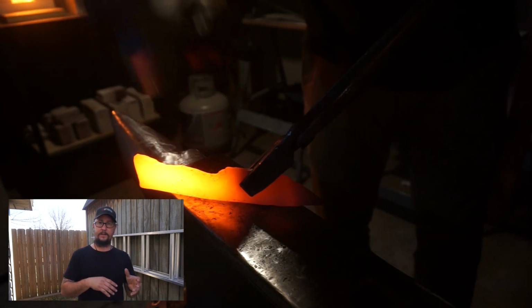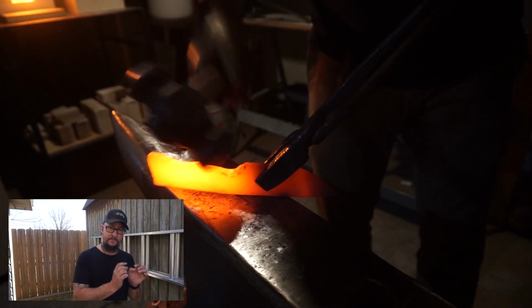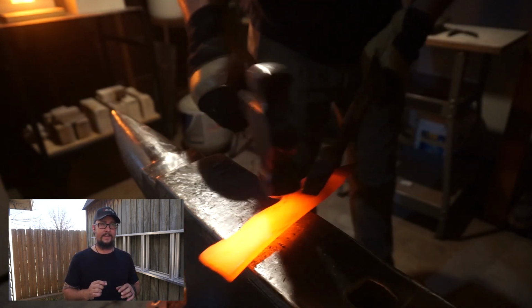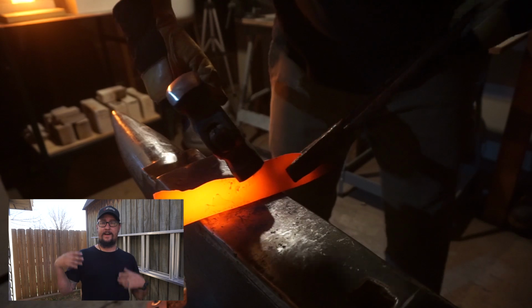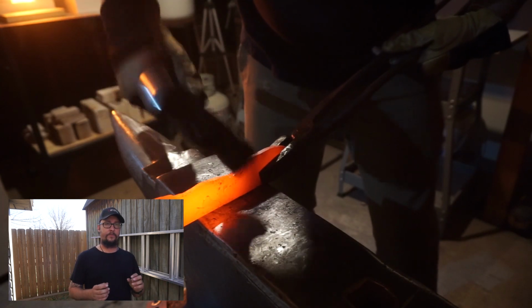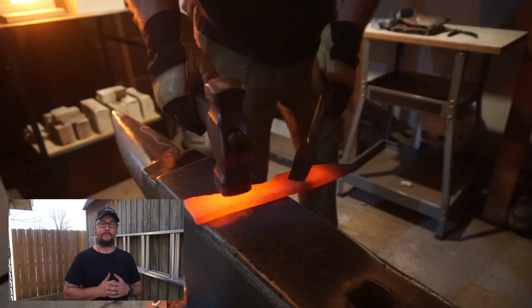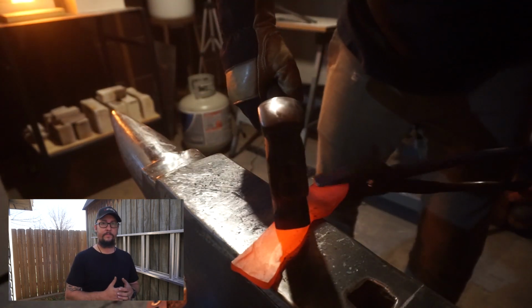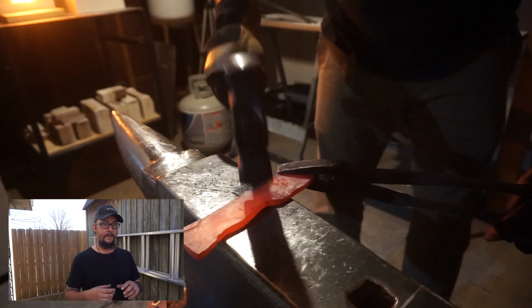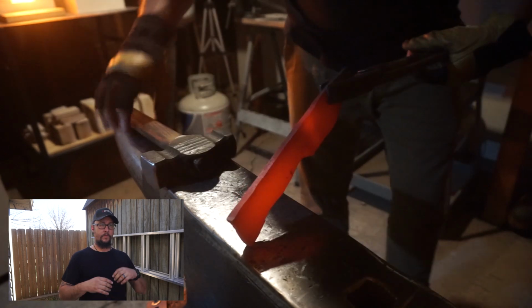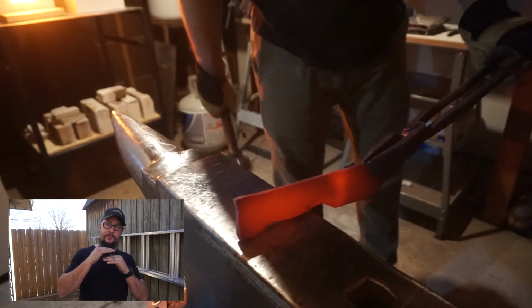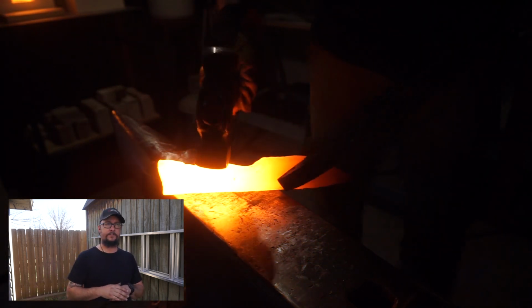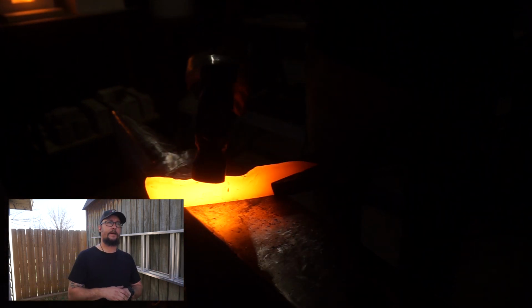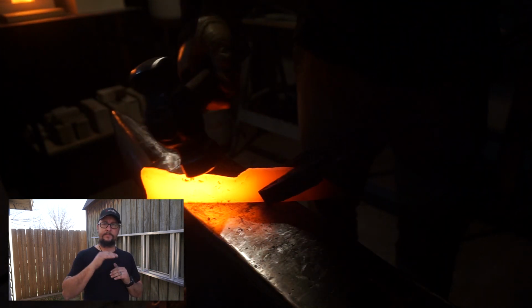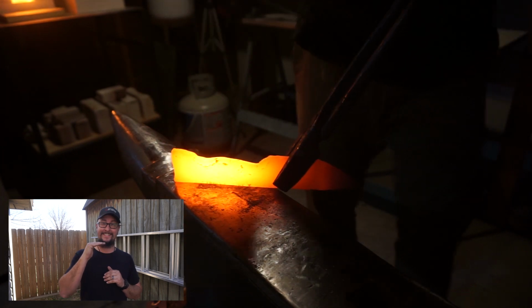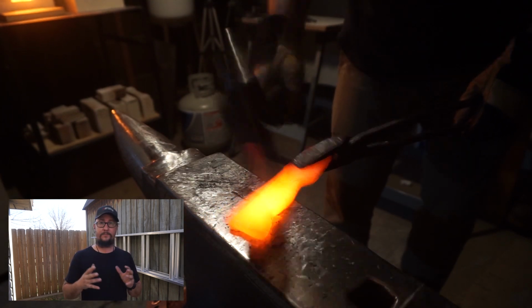Now, when it comes to other heat treating processes, this is why you need to do a little bit of research on the steel you're working with, because a lot of people will tell you, get some 1095, work with that. Well, 1095 requires a soaking process. That's another term that a lot of people don't really talk about. What they mean by soaking is whenever you get up to the actual temperature that you want to be before you quench it, which could be 1550 degrees, you want to bring it up to that temperature, and you want to keep it at that consistent temperature throughout the full blade for about 10 minutes.